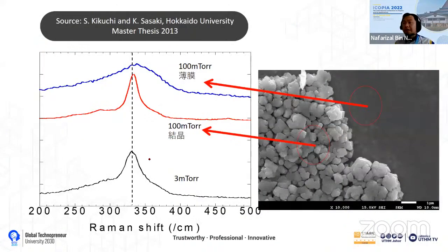Okay, and then when we study the Raman shifting, you can see that these nanoparticles are very crystalline, but on the flat surface here, the film is amorphous, right? You can see the broad spectrum here.